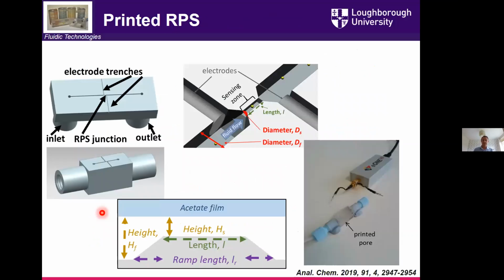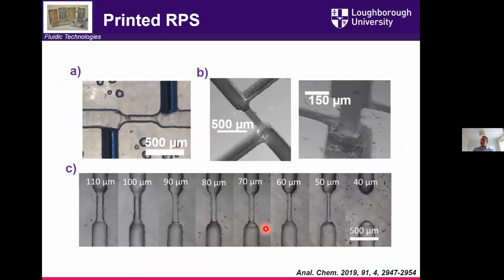And this is that same example, using those same features where we embed channels on the surface of a chip. We have screw threads, so we can plumb the outlets of our fluidic chips straight into this, characterize the droplets that we're making, and then they pass back out and carry on the reaction. And so this was really, again, us demonstrating, starting to flex our muscles into how do we fabricate 3D printed devices in this. To get narrow channels in SLA devices, you have to print them on the surface, is what we found.